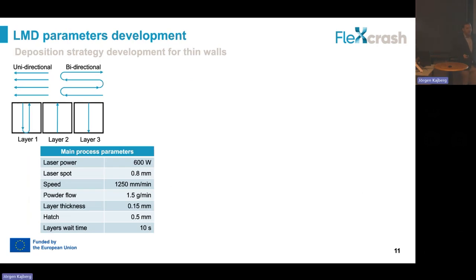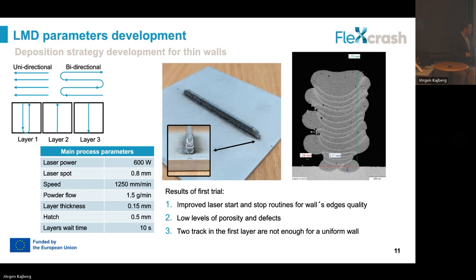In order to control this, we had to change the strategy that we use for the deposition. So add more tracks in the initial layers and then reduce the number of tracks in higher layers. From the cross-section, you can see the first results when we tried to have two tracks, one next to the other in the first layer. And here we had to optimize the distance between the two tracks. Our aim then was to achieve a wall with quite constant width.